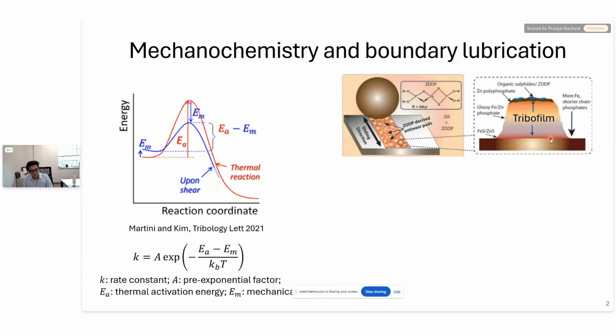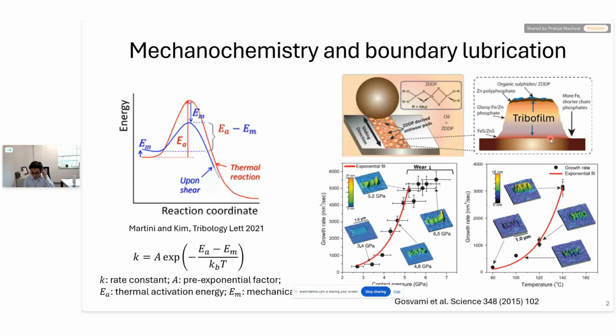In the past, the research group of Professor Robert Carpick at the University of Pennsylvania showed that the growth behavior of these tribofilms is strongly dependent on contact pressure and temperature. So as the contact stresses are increased, the growth rate of tribofilm increases exponentially. Similarly, temperature also provides that exponential boost to tribofilm formation.